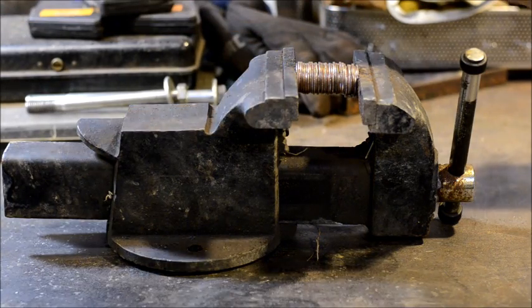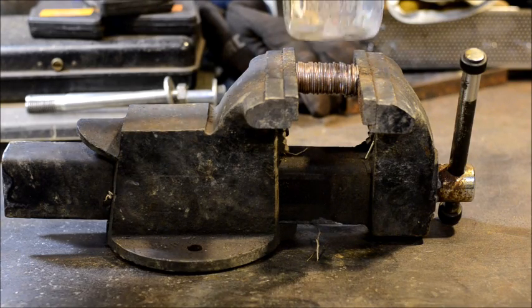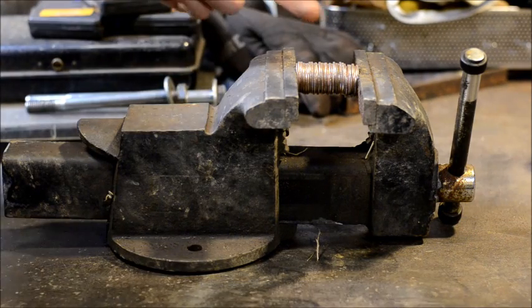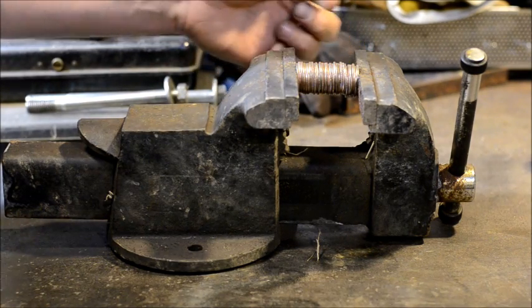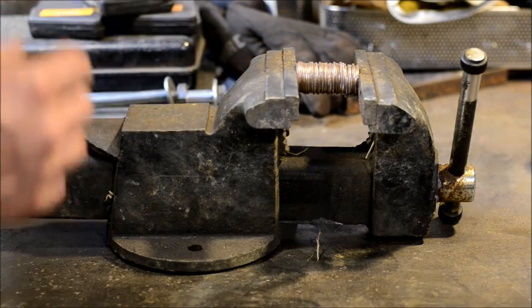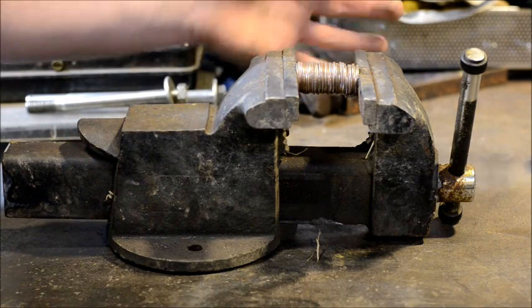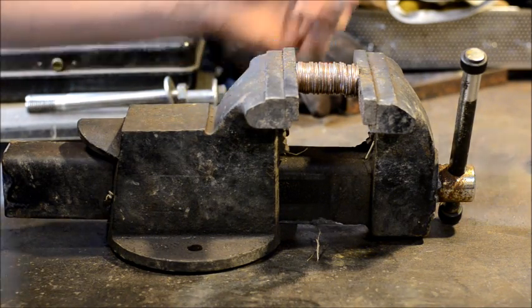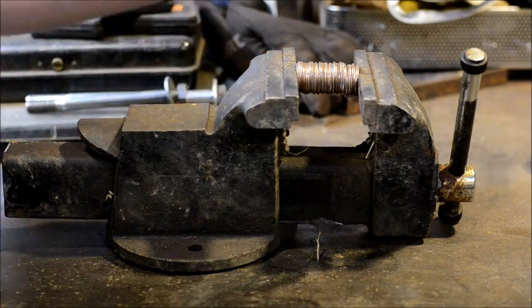It's very important that you clean your coins. If you don't, you're going to have problems with your coins not sticking — that's one of the biggest problems. Number two, and I'll go over this in further detail in part two of this series: this is not hard metal. You're not trying to whale on this thing to get sparks and molten metal flying everywhere, because you're actually losing nickel and copper — you're squirting it all over the place and not getting a bond. I'll go over that more when I cover welding in the vise in the second video.